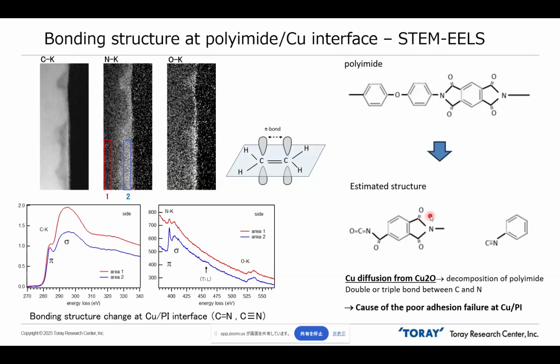So oxygen in the polyimide should be stolen by the copper ion. So finally, this triple bonding should be created. So in this case, we think the root cause is the copper diffusion from copper oxide.